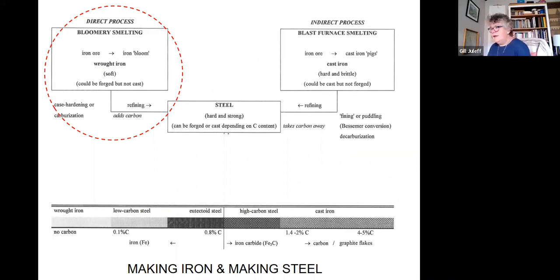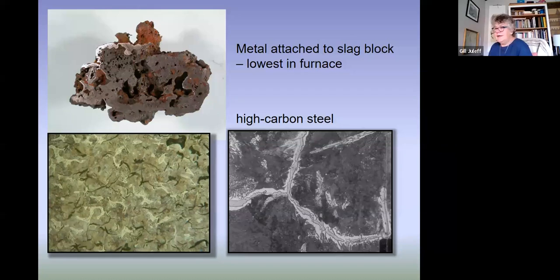However, we then went back and looked again at all of the stuff that had come from our furnace, and we found that actually half of the metal that we've made was still stuck to the slag at the bottom of the furnace. Clearly a shortcoming in our technique in that we weren't able to separate this metal, but this metal, when we analyze it, is high carbon steel, and it's been molten. And you can see that from the shape that it's forming here. It's been liquid, and it gives us a very, very different microstructure.